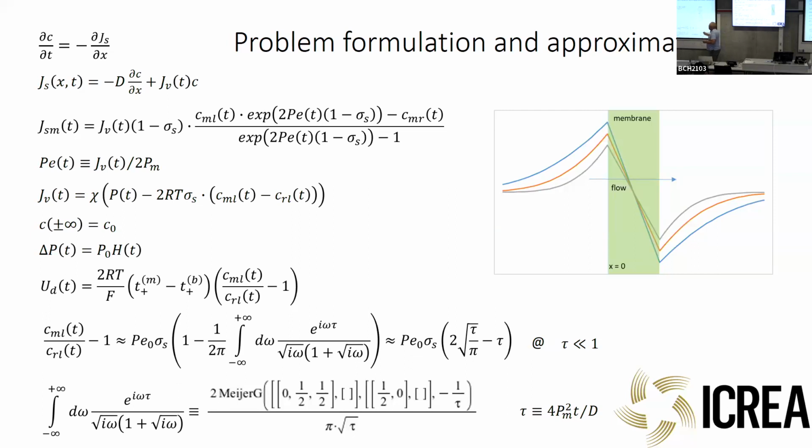Due to the fact that the so-called electrochemical current selectivity of the membrane is different from the electrolyte solution, this gives rise to some voltages. And these voltages occur on top of streaming potential. So initially you have just streaming potential without any concentration gradients, and then you have the buildup of these concentration gradients and the corresponding voltages.